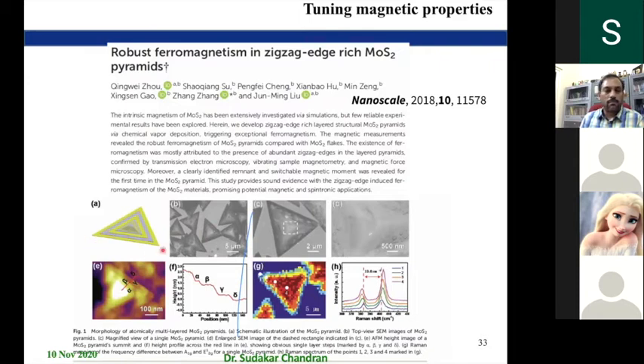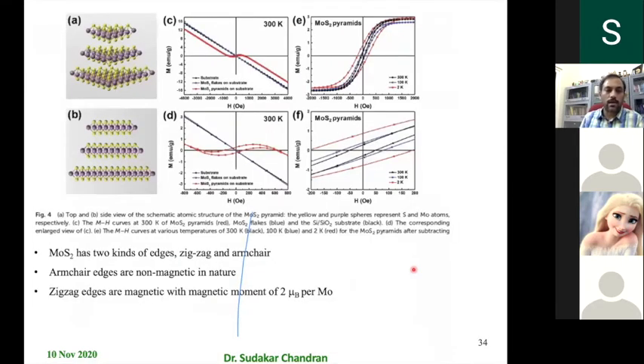So big sheet of layer, and then you have a lot of sheets stacked on top of it. So it forms a pyramidal structure. So in this case, the edges, each pyramid, as the size keeps on decreasing, you have a lot of edges, right? So these edges, they call zigzag edges, are many in these crystals, like you can see in this particular case, lots of edges, and therefore the zigzag edges have a ferromagnetic nature. So what they showed is, by changing the zigzag edge configuration, they made the ferromagnetic nature.